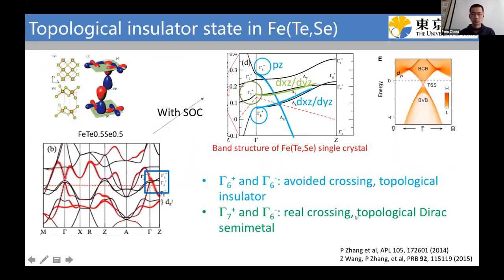In 2014 and 2015, we started to realize that there may be topological states in this material, in the material of iron, tellurium, selenium. In the calculations, we found that there is a pz band going down from the gamma point to the Z point along the gamma-Z direction. The key is that the pz band has a minus parity, while the three t2g d orbital bands have plus parity. So when they cross, there will be a band inversion. For the bottom crossing, there is an SOC gap opening, so it forms a topological insulator state. For the middle crossing, the crossing is protected by the fourfold rotation symmetry, so it forms a Dirac semimetal state.